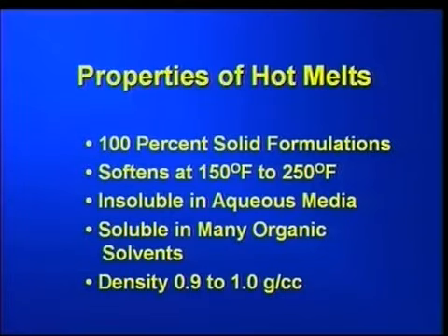Most of the hot melts are insoluble in aqueous media under any pH conditions, but they dissolve readily in many organic solvents like dichloromethane, trichloroethane, perchloroethylene, chloroform, and so on. The density of hot melt could vary between 0.9 and 1 gram per cc.